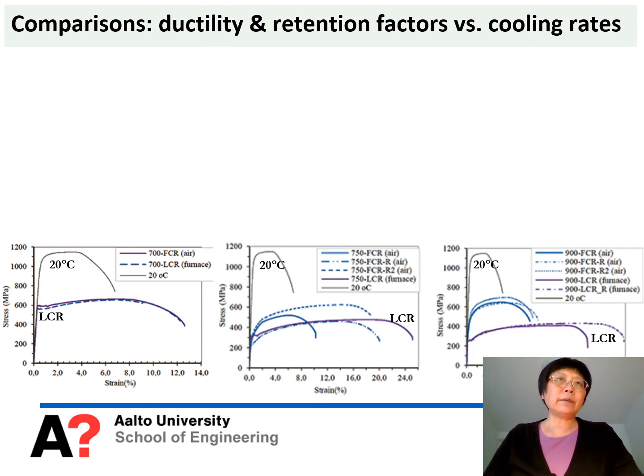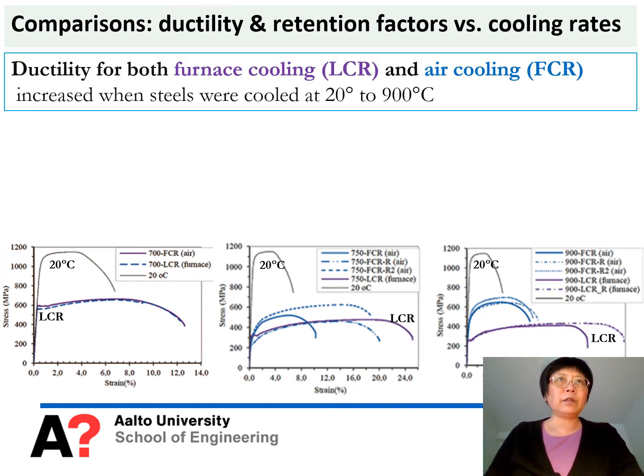And this slide basically shows the stress-strain curves at some selected cooling temperatures. The left-hand side shows 700 degrees, the middle is 750 degrees, and the right one is about 900 degrees. So it can be seen that ductility for both furnace cooling and air cooling increased when the steel was cooled from 20 degrees to 900 degrees.